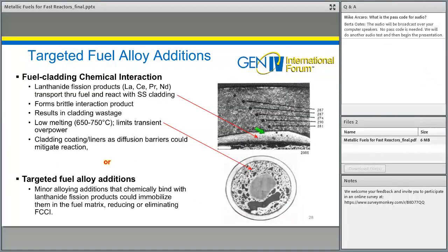The other thing that we've been looking at are what I call these targeted fuel alloy additions. Those who are familiar with metallic fuel performance know that one of the limiting issues that we have is fuel cladding chemical interaction. So this is a piece of cladding here. The fuel would be down below it. And not the fuel alloy itself, but specifically the rare earth fission products, which are created by fission, tend to migrate to the cladding inner surface and react with the cladding inner surface.